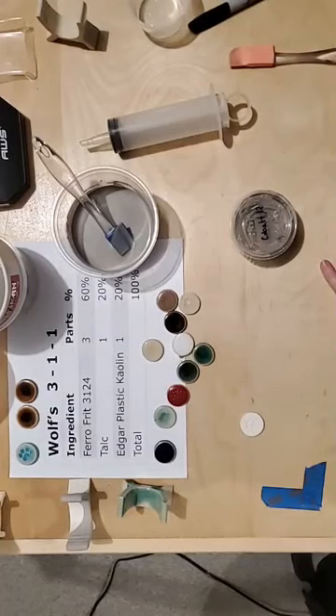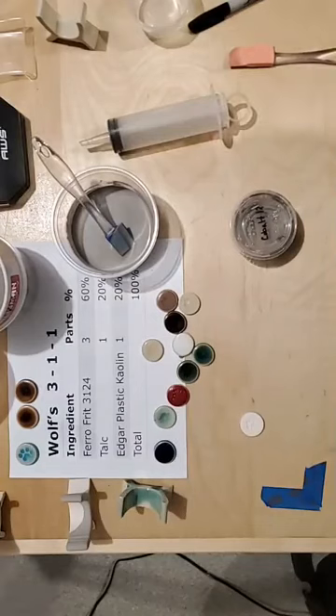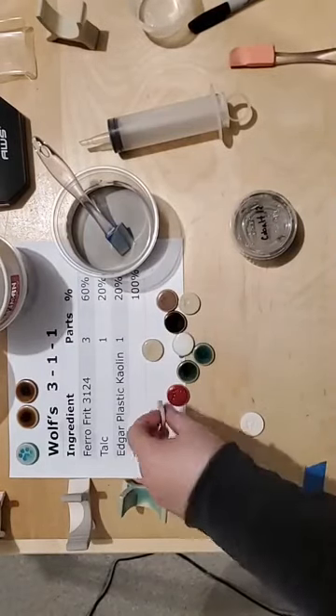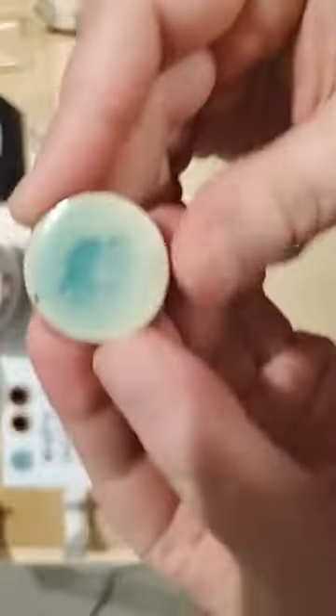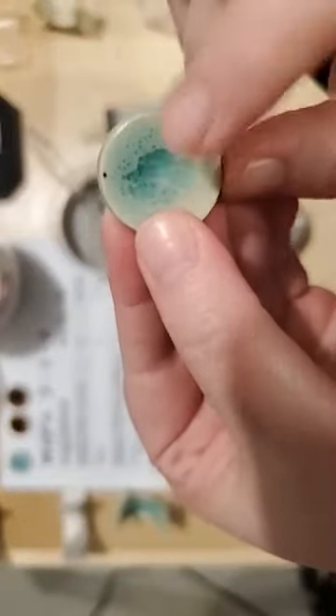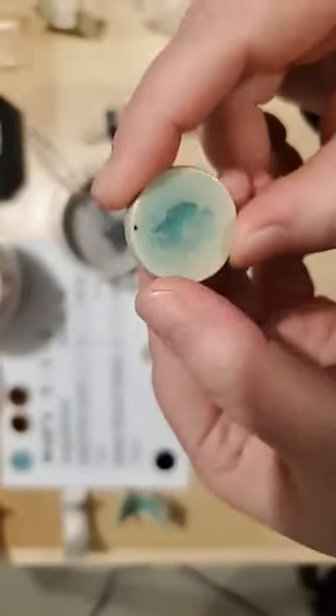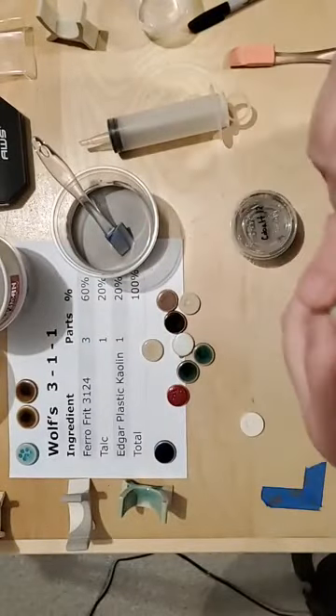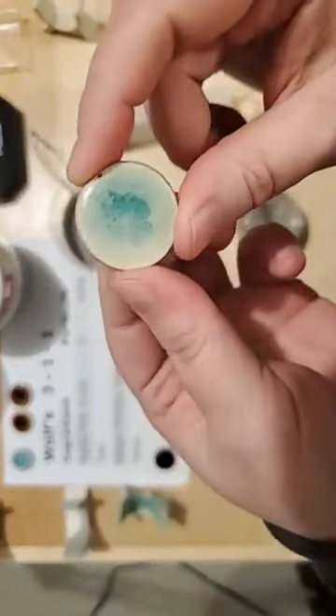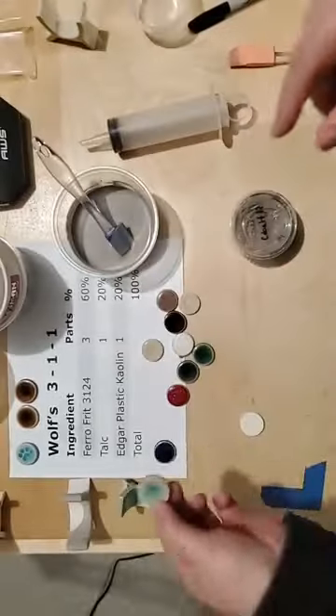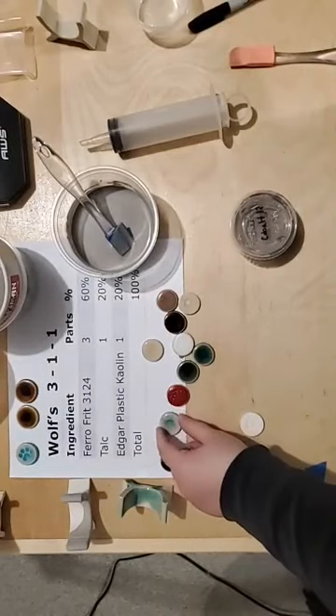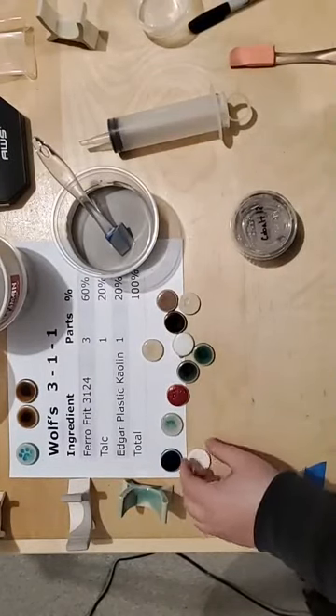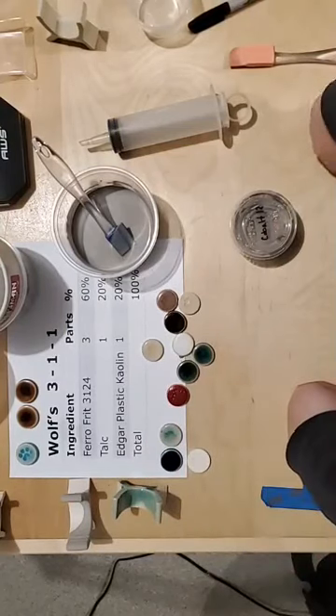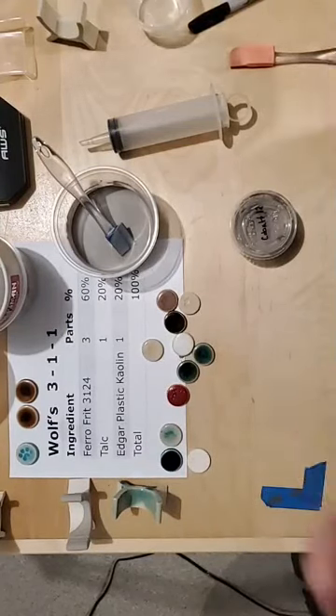If I did a hold at the top and a controlled cooling, would it help with the bubbles? Asks Heather. Possibly. Sometimes a hold at the top does help with bubbles. It allows the glaze to stay molten long enough to let these bubbles clear and the pits heal. Sometimes that happens. Controlled cooling may also allow for more time for the bubbles to clear. However, that can also introduce other issues. If you do controlled cooling, you can sometimes end up with crystal growth.